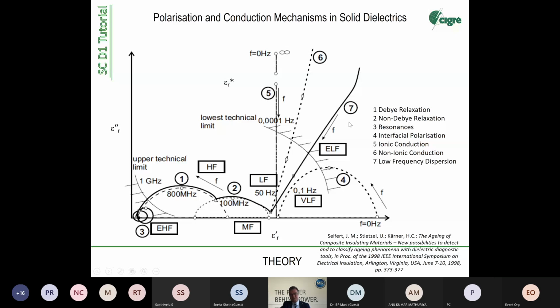7 is a low frequency dispersion. And this one is the one that we applied for our analysis. It's actually a mixture between the Maxwell-Wagner effect and the ionic conduction. And this is where the theory and the engineering equations come together. So it's very difficult to make just one model for a complex material like a polymeric material. So this is why in engineering, we concentrated on this line here. So this is what we see in the later results from the lowest technical detection limit, which is around 0.0001 hertz, 10 to the minus 4 hertz, to the technical frequency 50 hertz, until you get a gain again in the permittivity, especially in the loss function. So we see in the results mainly this U-shaped curve.